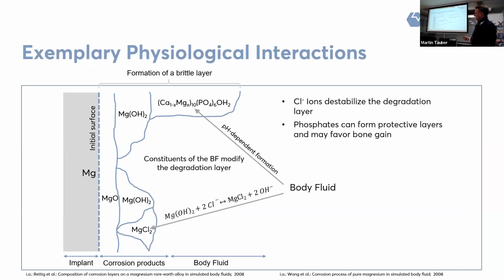First of all, there's a reaction of the magnesium hydroxide layer with chlorine ions. What happens is that magnesium chloride is forming on the implant surface. But this compound is highly soluble, so it will disappear. And you can easily imagine that what happens here is a destabilization of the already cracky degradation layer on top. So it's basically a degradation booster. Degradation will happen more rapidly in vivo due to the chlorine ions.